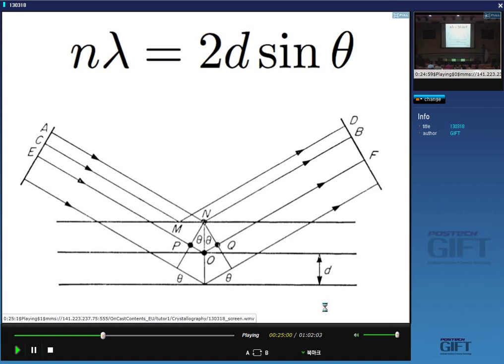Then all these beams which hit the top layer are traveling exactly the same distance. Yeah. So you start from here and you reach this point here, add up this distance, that's exactly the same as this distance here. Right? Therefore, these are in phase. Yeah. The peaks of the waves coincide with the peaks of the other wave, and they reinforce. This, on the other hand, has a path difference which is PO and OQ different from this beam here. Right? It's traveling an extra distance PO plus OQ compared with this beam here. So this will be out of phase with anything being reflected from this layer here.